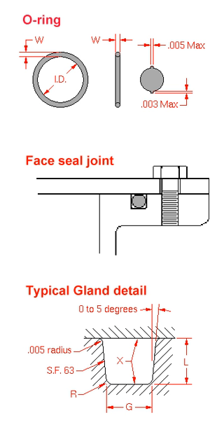When O-rings were selling at a premium because of novelty, lack of efficient manufacturing processes, and high labor content, square rings were introduced as an economical substitution. The square ring is typically manufactured by molding an elastomer sleeve which is then lathe cut. This style of seal is sometimes less expensive to manufacture with certain materials and molding technologies — compression molding, transfer molding, injection molding — especially in low volumes. The physical sealing performance of square rings in static applications is superior to that of O-rings; however, in dynamic applications it is inferior. Square rings are usually used only in dynamic applications as energizers in cap seal assemblies.